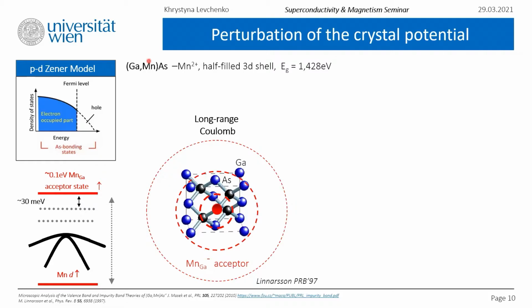First is the long-range Coulomb contribution. It's a long-range hydrogenic-like potential of a single acceptor in gallium arsenide, which produces a bound state around 30 milli-electron volts above the valence band.